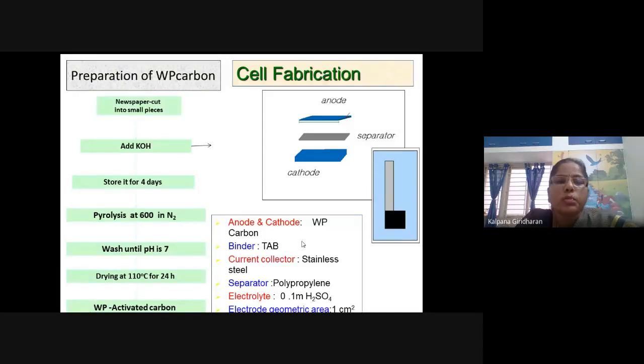The newspaper is cut into small pieces. We added KOH and soaked it for 4 days, and we pyrolyzed at 600 degrees Celsius in nitrogen atmosphere. We washed until the pH is 7 and dried at 110 degrees Celsius, and we get a pure activated carbon. So this is how we prepare our electrode.